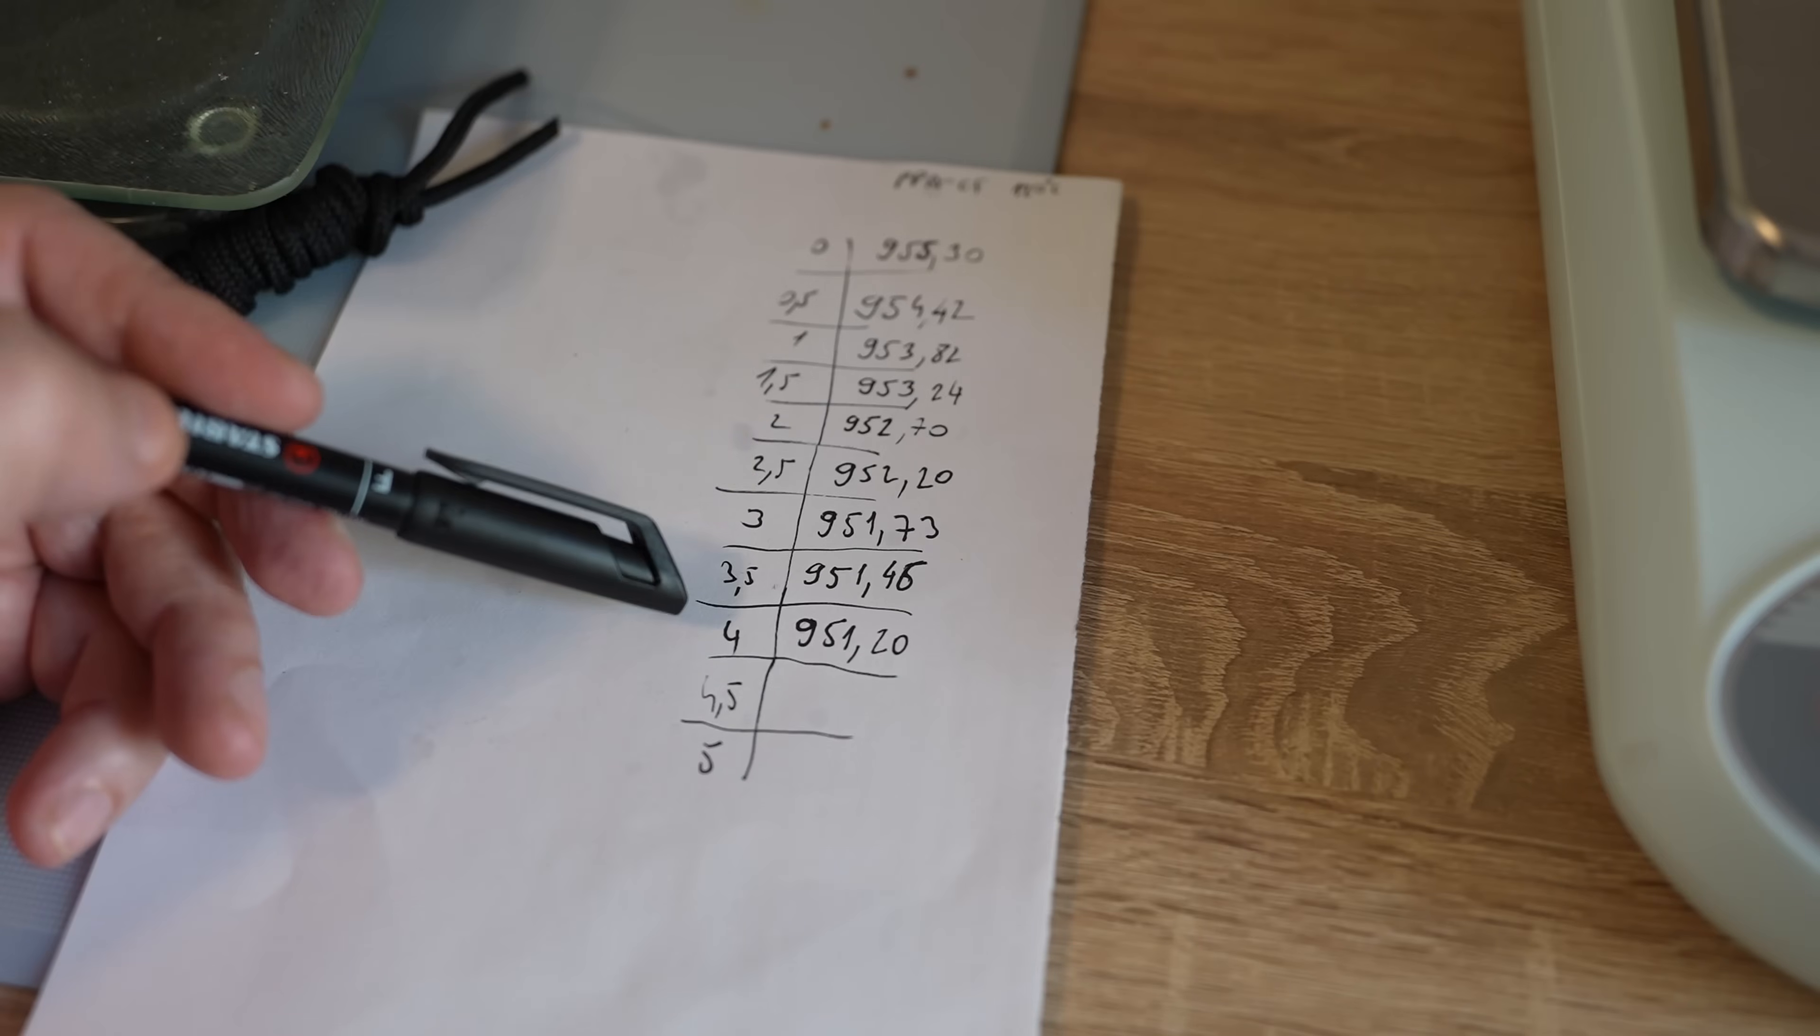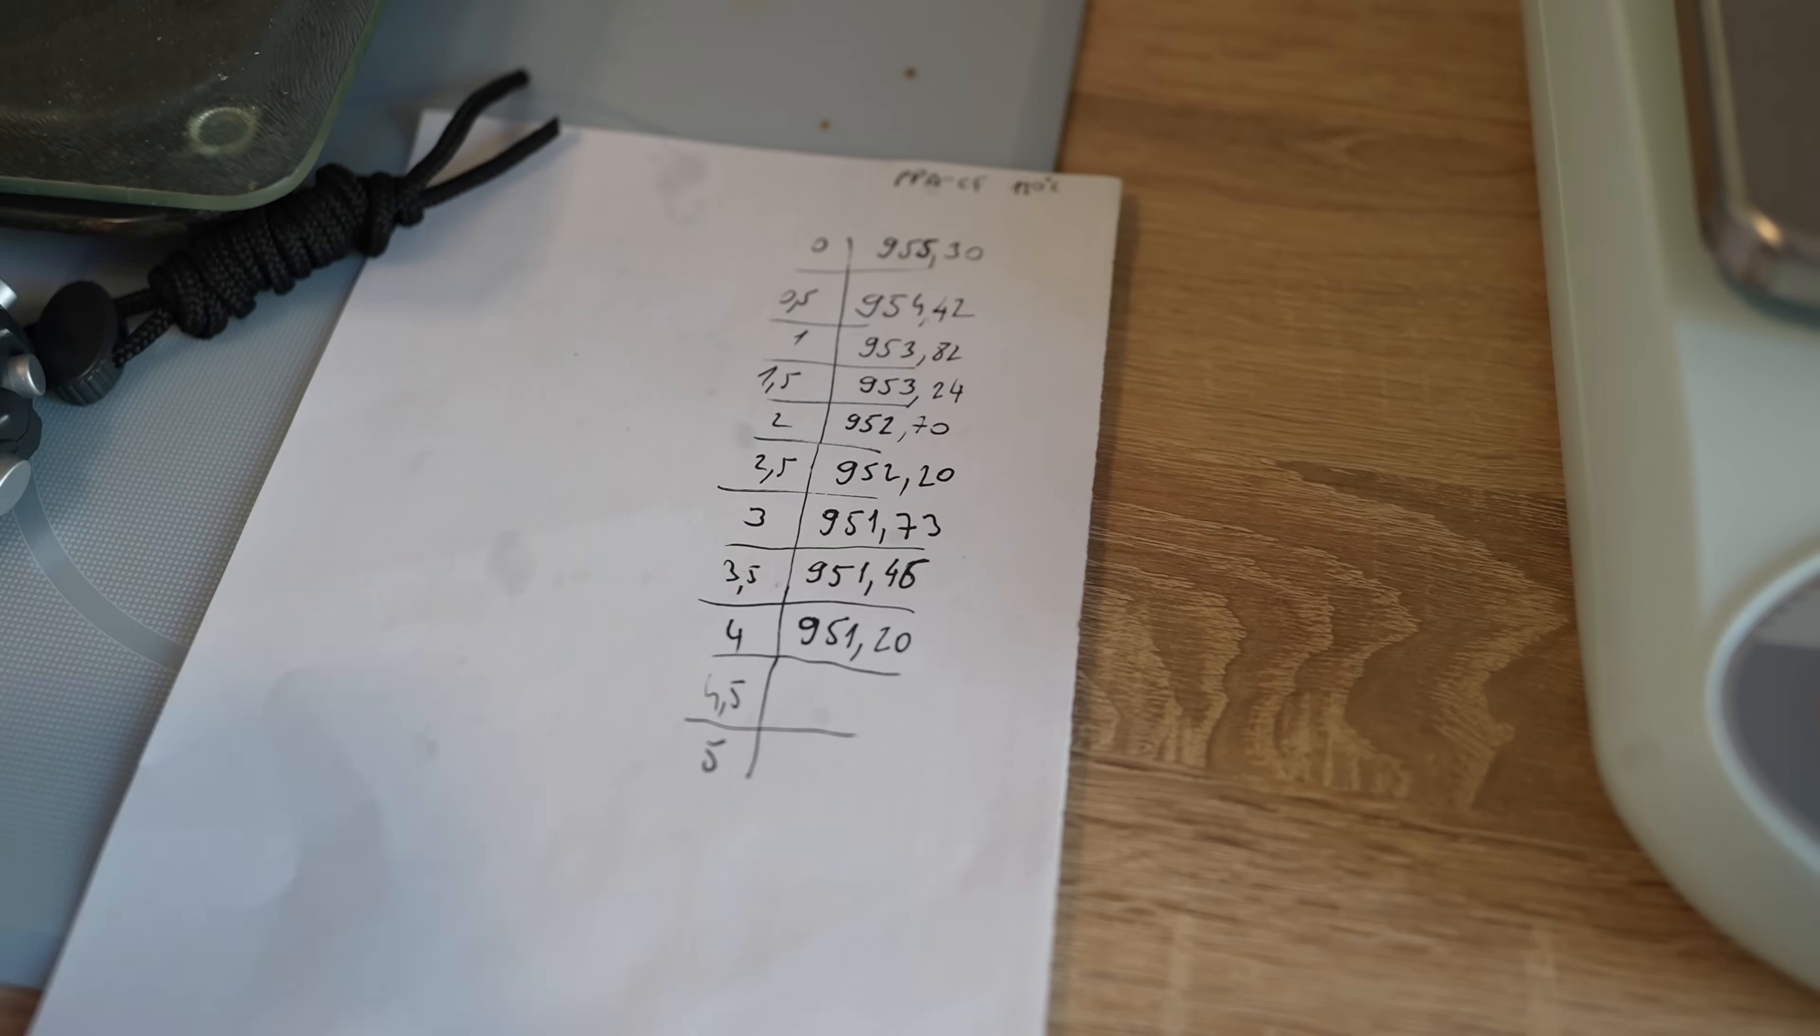Only now after 4 hours of drying I can see some slowing down in the weight loss. So maybe soon it will make sense to stop the drying and start the printing, maybe after 1 hour. Of course it will not be perfectly dry, but I will not get significantly better results if I dry it 4 hours more. And the last measuring after 5 hours, 950.86, so definitely it slowed down with the weight loss. It's ready for printing.